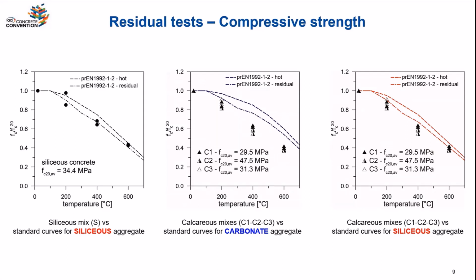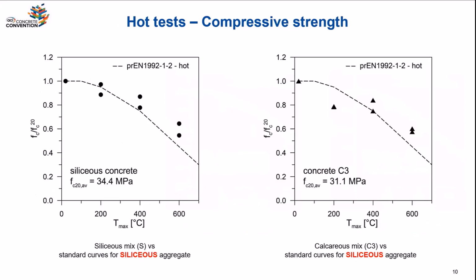This was already known largely, and actually in the next version of Eurocode, the prEN 1992 that you see here, they will have a curve for residual strength which is lower than the hot curve. But that's also what we found in our experiments. These are the hot values, so just the measurements at elevated temperature. So here, nothing new, and we found that the provisions in the codes are mostly conservative or appropriate.